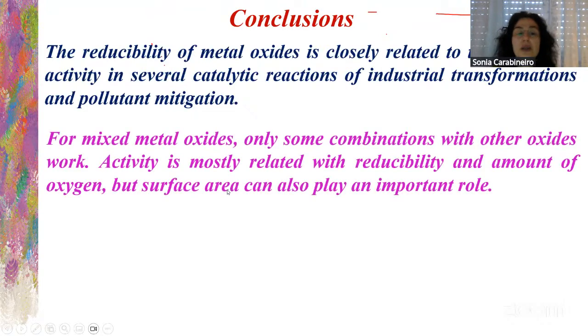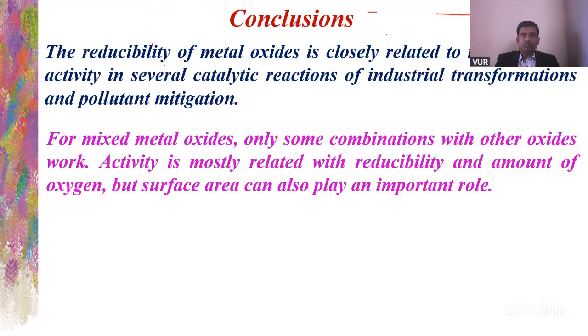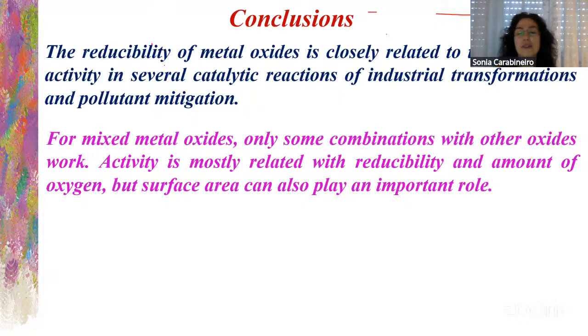And for mixed metal oxides, we saw that only some combinations work, because sometimes, like when we added samarium, it decreased the activity. So activity is mostly related with reducibility and the amount of oxygen, okay? But also the surface area of the materials can play an important role.